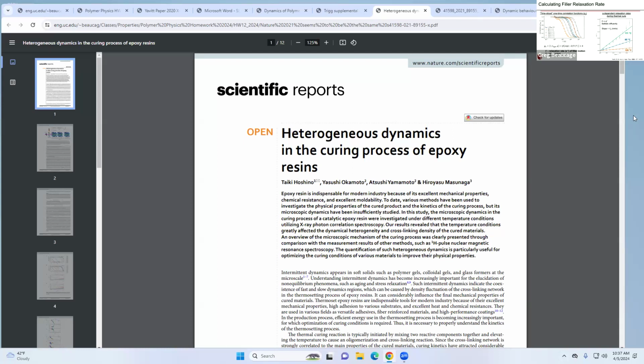So that's actually the part before you get to the curing reaction. So we're heating it up. The curing reaction hasn't initiated yet. This is just thermally induced behavior, right? You heat up something, it moves around faster. So we actually saw an increase in the dynamics before we hit that critical curing temperature. And then once we hit 120, where the reaction starts actually curing, the dynamics dropped a lot down to the slow behavior. So there should be a plot describing that whole story.